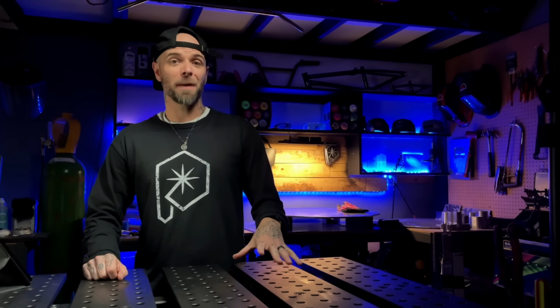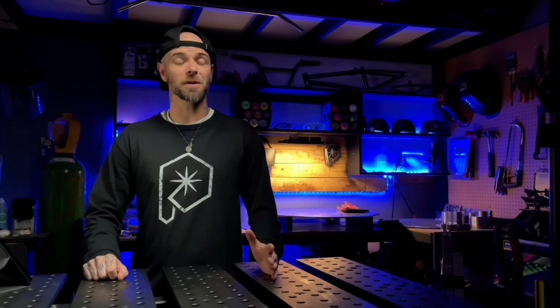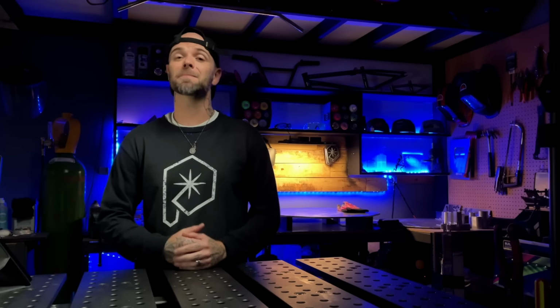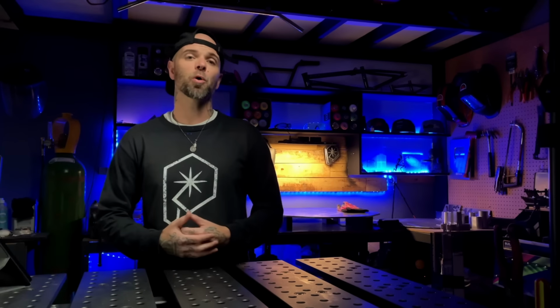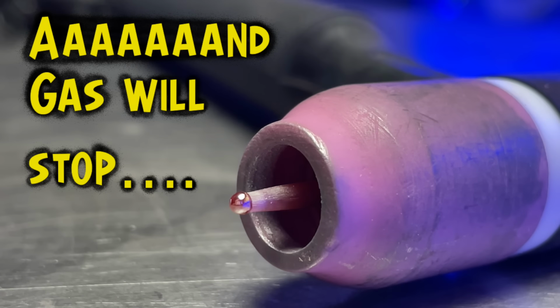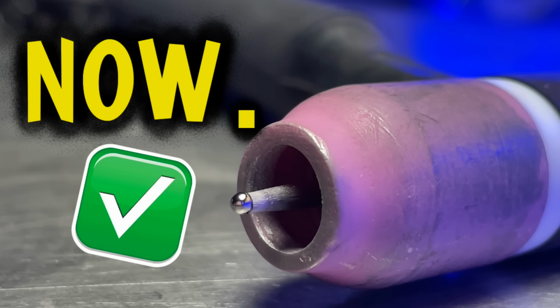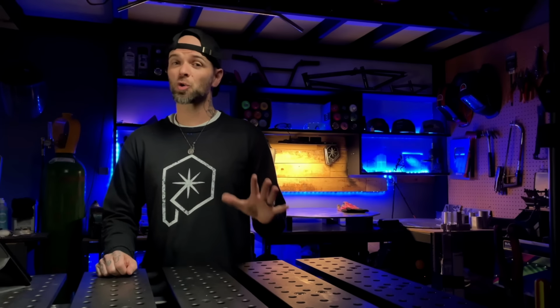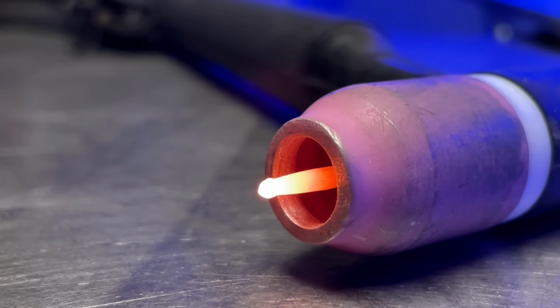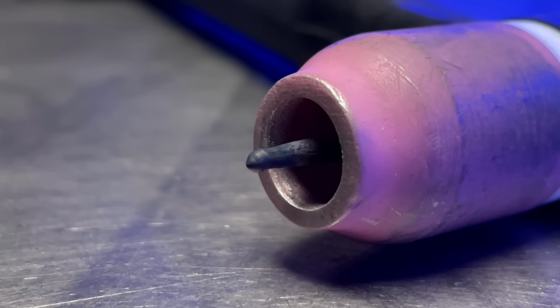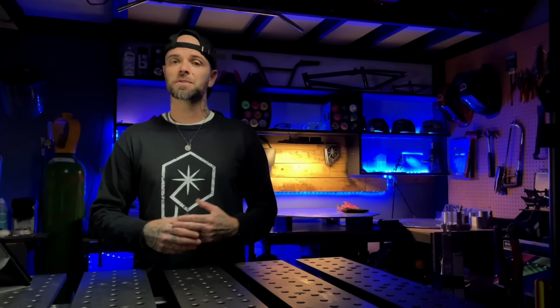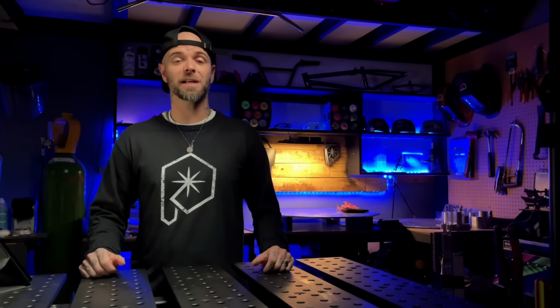Anytime we finish a pass, we have to keep our tungsten completely shielded by post flow. Using the timer to set this cycle on our machine is going to help us do this so we can keep that tungsten clean. Typically, I like having my post flow cycle run usually an extra second or so after my tungsten is finished glowing red hot. And yes, I pay for my own gas. If the gas flow is cut short in this brief little window, there's absolutely no way around it. Contamination forms immediately. If you are unsure that you have enough post flow running, set your machine for an extra couple seconds just to be safe.